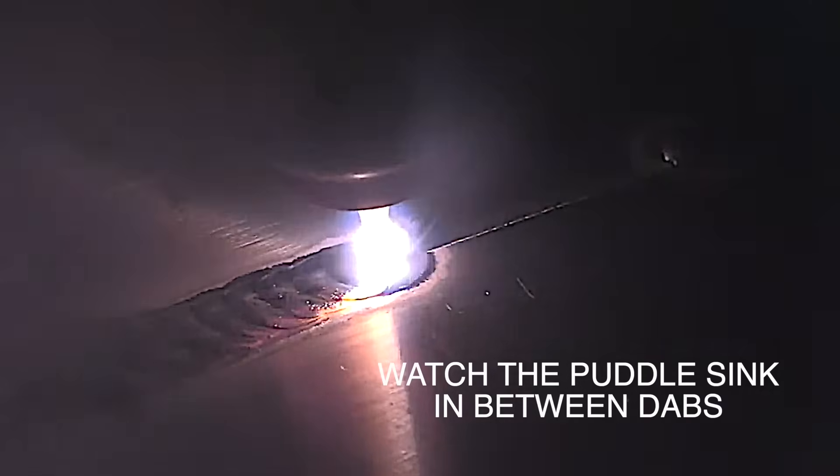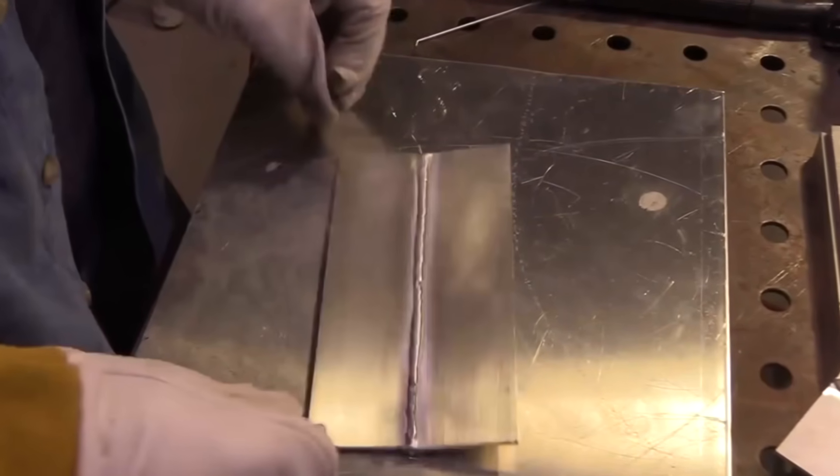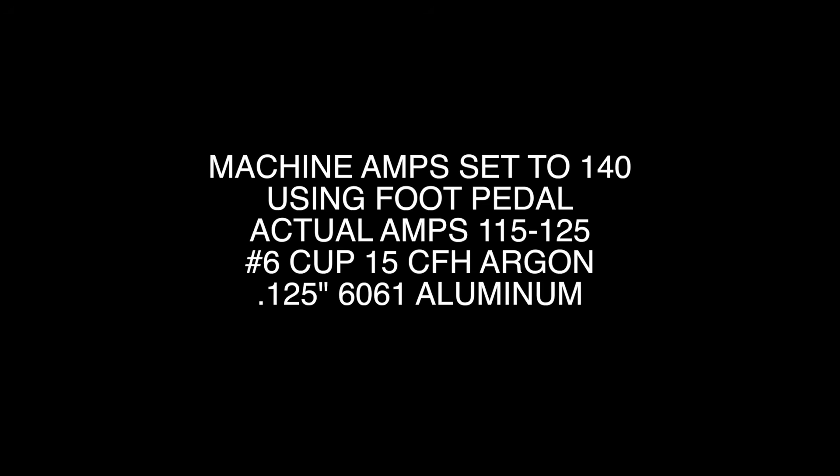Each time I move ahead in between dabs, it just sinks down. And I'm using that same technique where I raise and lower the electrode. I believe I was set on about 140 amps, but I was using the foot pedal for that.